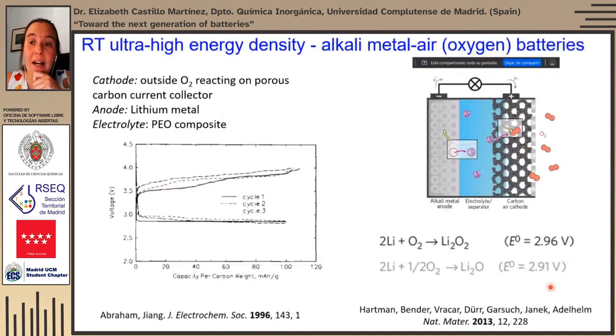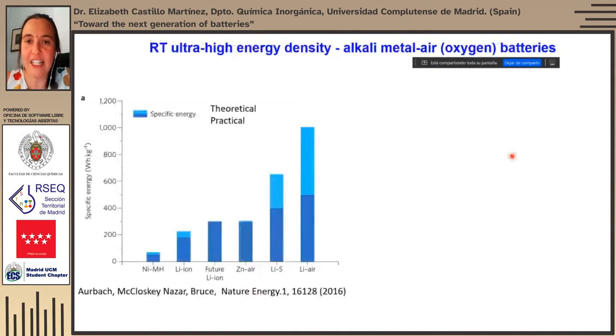On the other hand, the lithium-air batteries, which were first shown in 1996 by Professor Abraham, have an even higher redox voltage, very close to 3 volts, and similarly high theoretical capacities based on the weight. However, if we think that we are taking the oxygen from the atmosphere, we somehow have an infinite theoretical capacity. But actually, lithium in contact with oxygen is forming, most of the time, lithium peroxide. And this lithium peroxide is a solid that, once in the battery, does contribute to the weight and to the volume of the battery. So the capacity is actually not infinite.